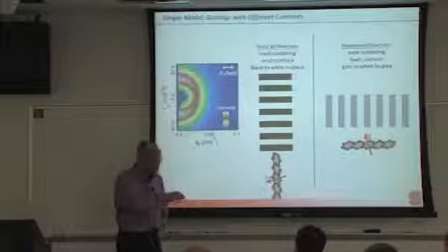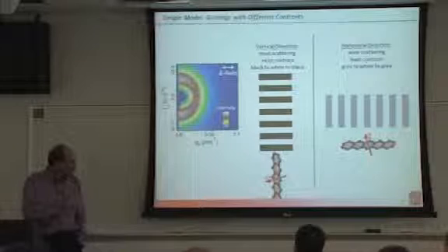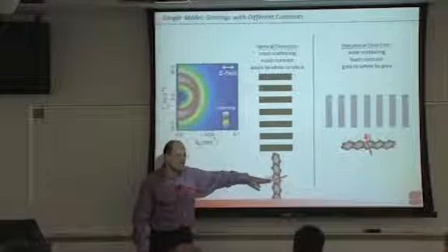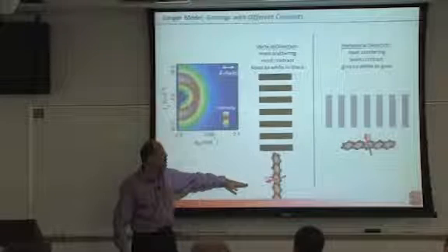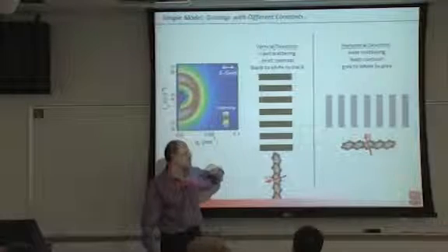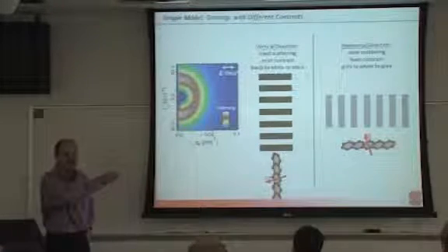And so let's just think a bit what that could be. If I make a grating of pentacene molecules with nothing, okay, white would be, let's say, vacuum, and I line this up so that my transition dipole moment is parallel to my electric field, and therefore I get high absorption. If I had an energy where I get high absorption, I would get high absorption, nothing, high absorption, nothing. I rotate that pattern. Now my transition dipole moment would be perpendicular, so I get lower absorption, nothing, lower absorption. So obviously I get more scattering in the vertical direction than in the horizontal direction.